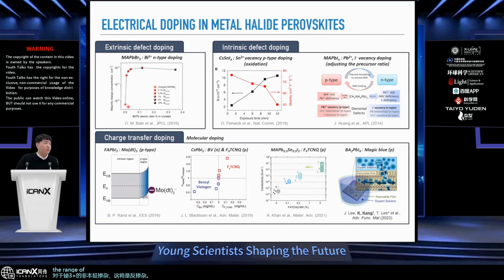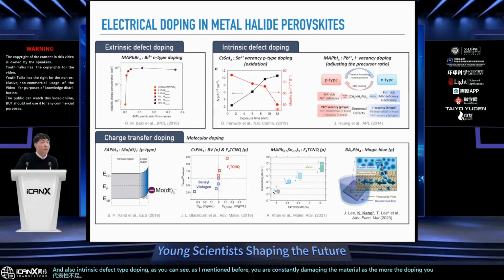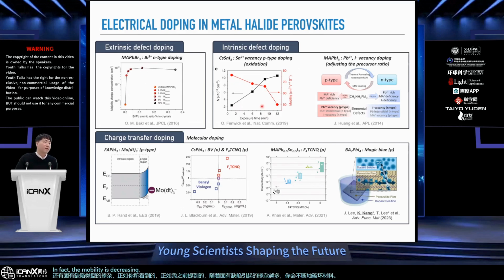The range of conductivity or charge carrier concentration that can be tuned is only up to 2 orders of magnitude, for example, compared to, let's say, 6 or 7 orders of magnitude that silicon can achieve. It's very underrepresented. And also intrinsic defect type doping, as mentioned before, you are constantly damaging the material. The more doping you induce by intrinsic defects, the more the mobility decreases, which reflects the fact that you're just damaging the material constantly.